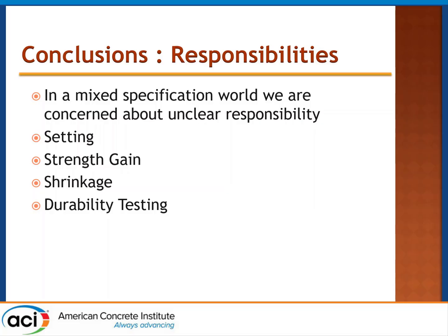Ward Malisch and Bruce, when they were at ASCC, and when I was chairing the P2P committee for NRMCA, put together a document that talked about what your concrete is going to do at 70 degrees, at 45 degrees, and at 90 degrees. So you had a skeleton for having that very discussion. Because if you find out that it's set so fast that you can't get anything done, or it takes 3 days to set, that has a tendency to interfere with the schedule.